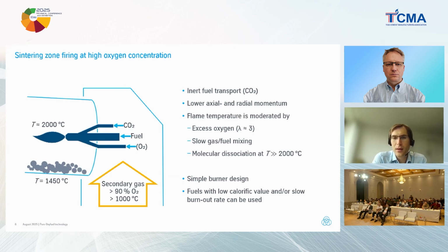secondary air, all the oxidizer is fed to the kiln, while only roughly 1/3 of the oxidizer is consumed by combustion. So the flame temperature actually is moderated by this very high oxygen excess, and all the oxygen which is not taking part in the combustion still needs to be heated up, like the nitrogen nowadays in the sintering zone. And by this approach, we can maintain the same temperature in the sintering zone like in nowadays conventional clinker kilns. There's some other modifications.